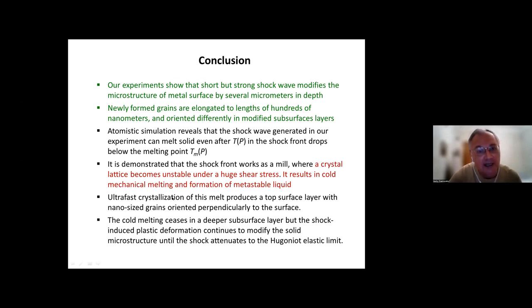So ultrafast crystallization after this melting produces a surface layer with nano-sized grains, which did not exist before. They are oriented specifically perpendicular to the surface, and we believe such surface modification can significantly improve the mechanical properties of the material. Thank you very much.